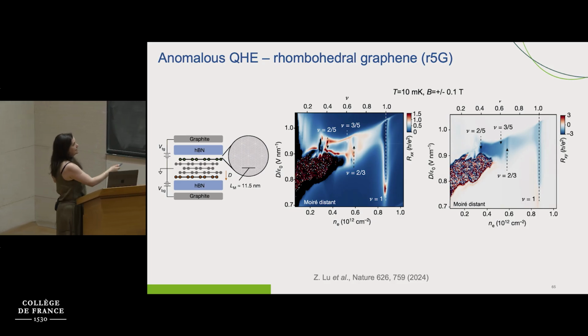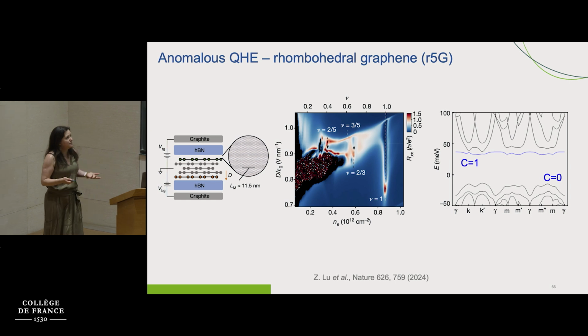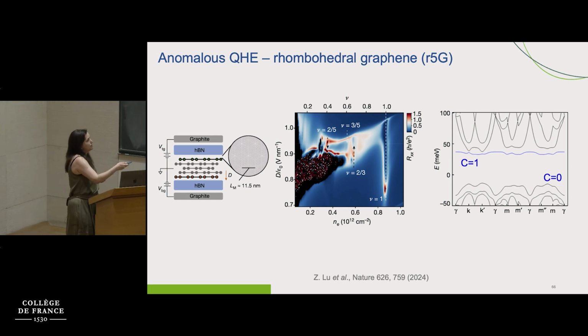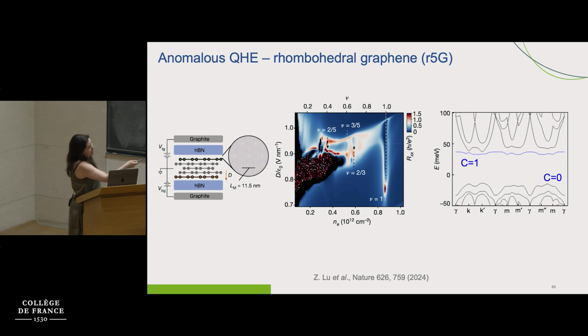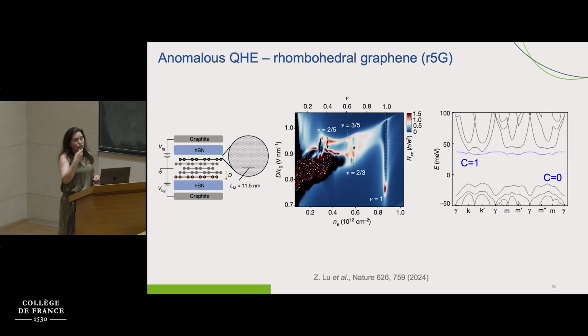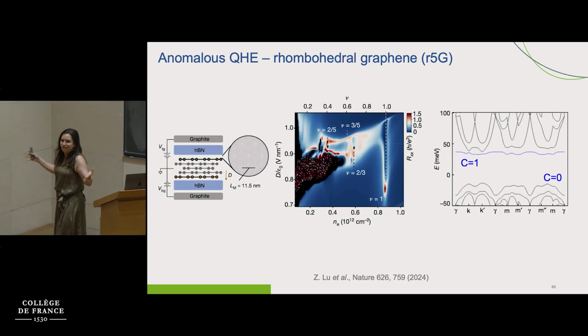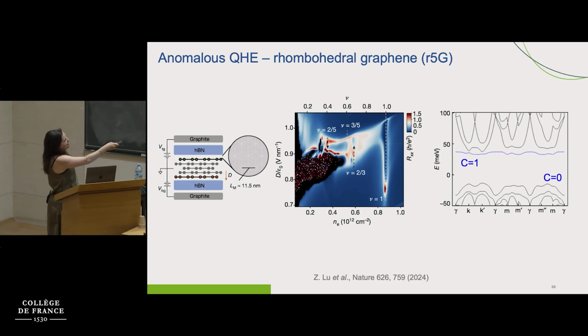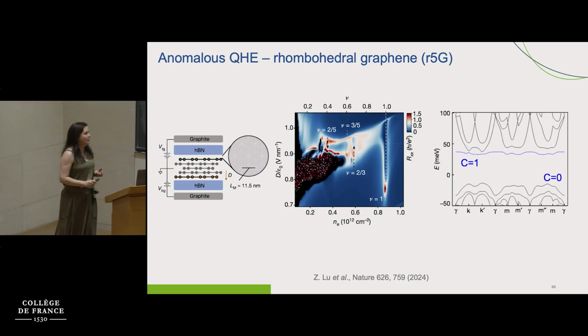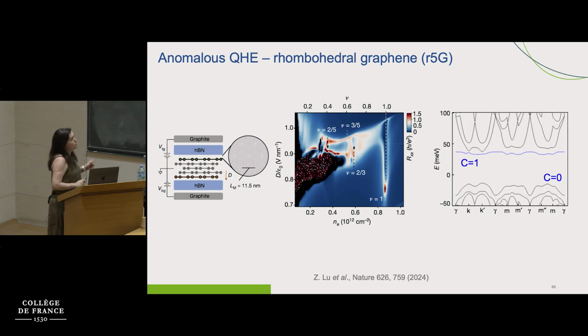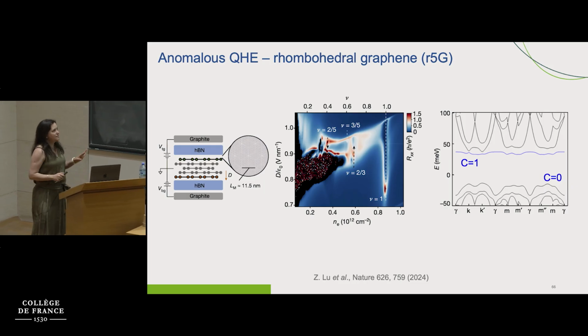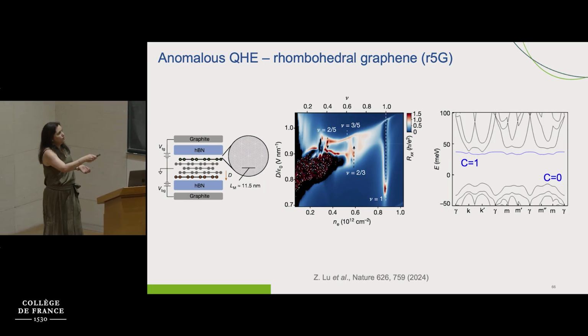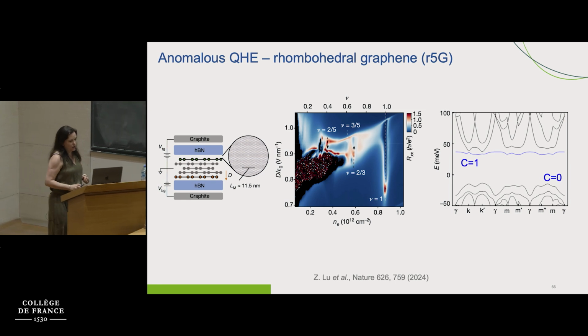Now to explain this, we can perform some numerical simulations of the system, and we find that we are going to have, in fact, a non-trivial flat band with a bunch of trivial bands around, as Antoine said before. So this flat band might be responsible for observing this integer quantum anomalous Hall state. However, it's not necessarily the reason why we observe the fractional Hall effect.